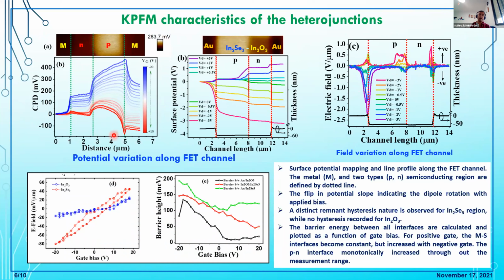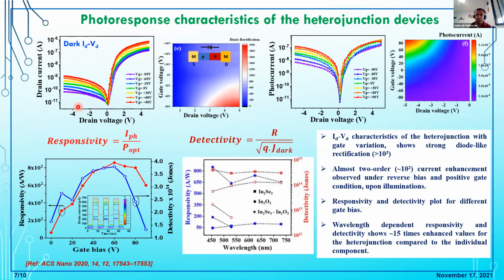Then we characterized the memory effect of the indium selenide part and the indium oxide part, and we see there is a hysteresis loop for the indium selenide part, whereas there is no hysteresis for the indium oxide part. We also tested the photoresponsivity of these heterojunctions, and we have an almost 15 times photoresponsivity enhancement. Also, we have a wide band photoresponse over the 450 nanometer to 750 nanometer range.